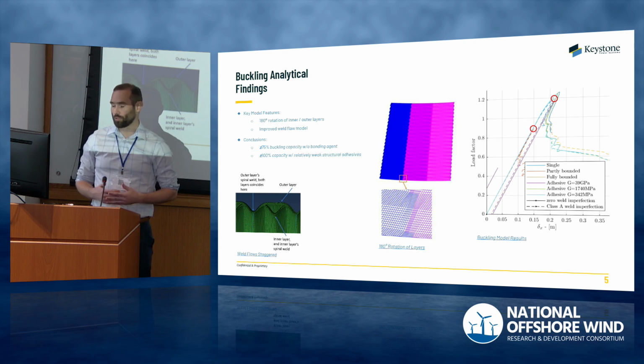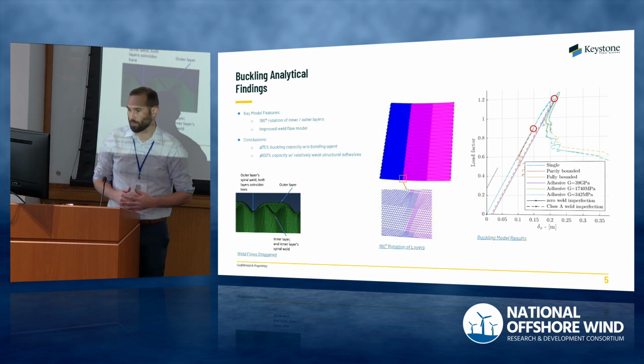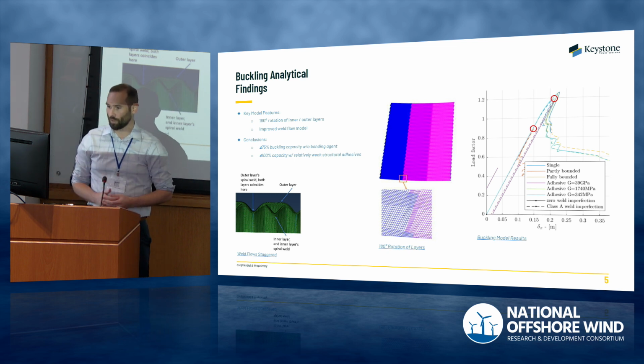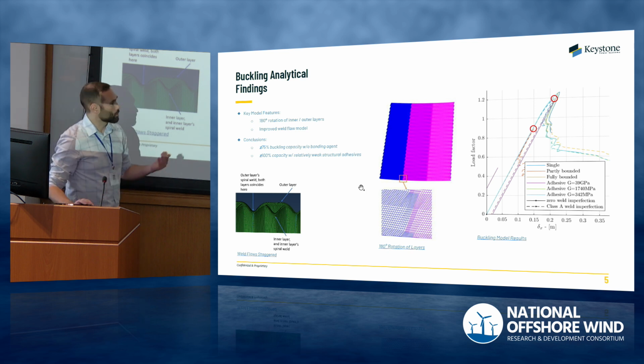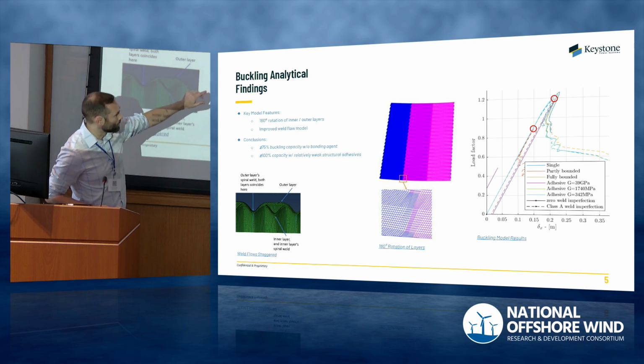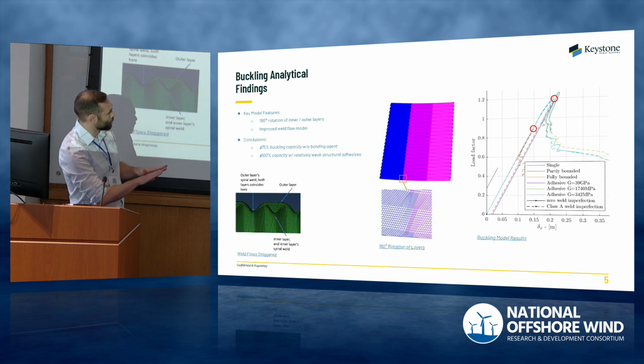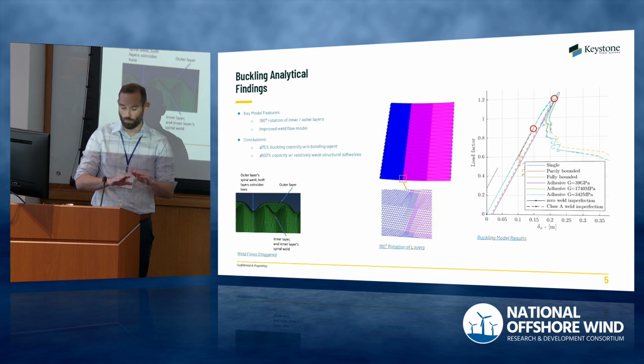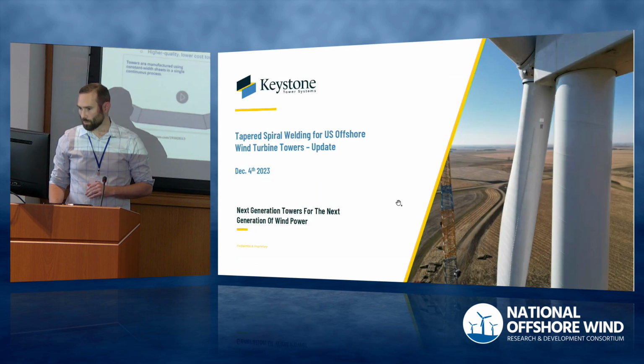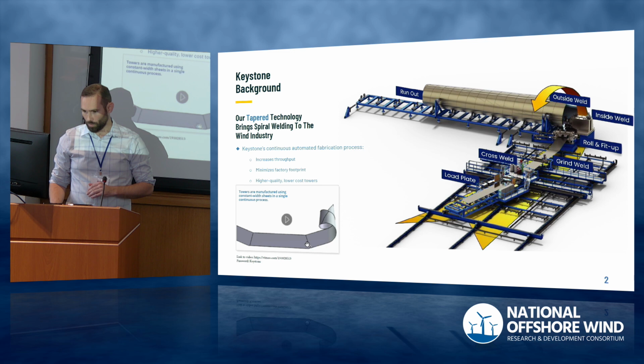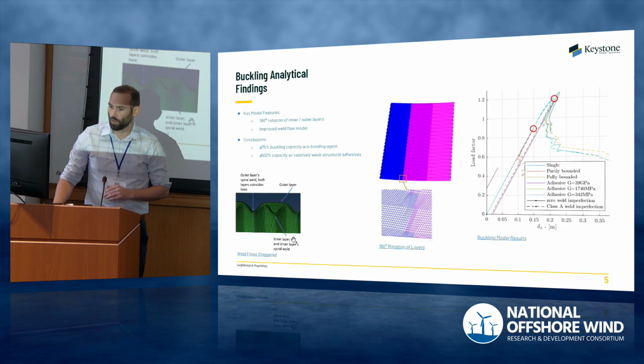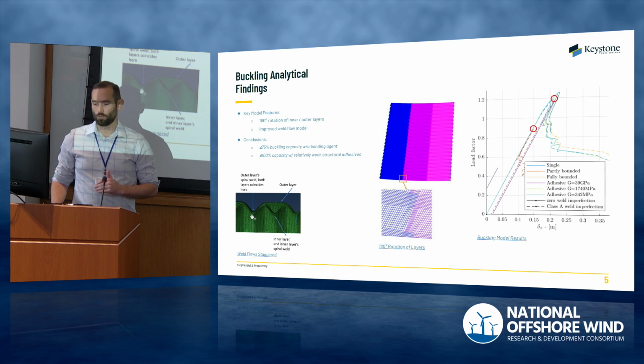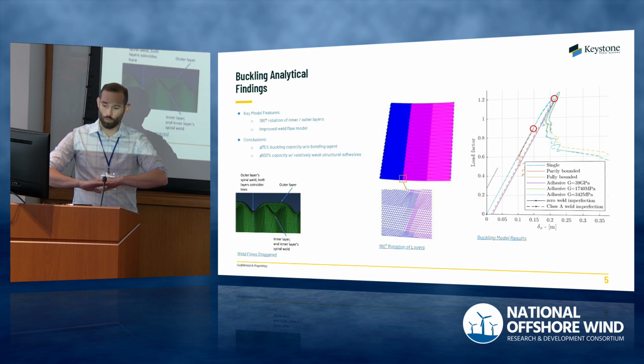And so what we've modeled is, and I should give credit to Johns Hopkins University, Ben Schaefer, for PIing this part of the research. So this is a two-layer tower, sort of unwrapped into a two-dimensional plane, and the blue layer is offset from the cyan layer by 180 degrees, or half of a sheet width. So going back up to this, the second layer would basically be offset by half of this sheet width. And that detail shows you'd have sort of staggering of helical welds.